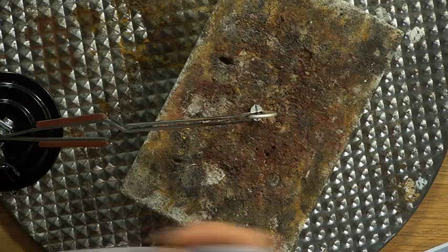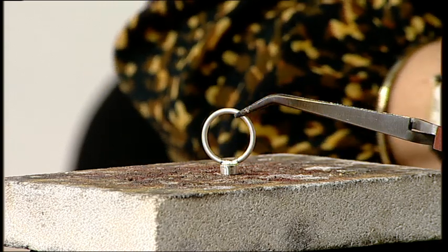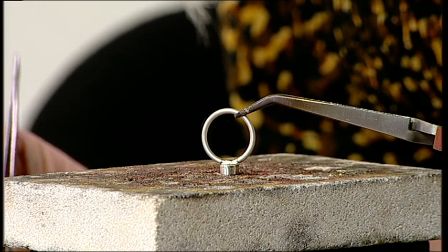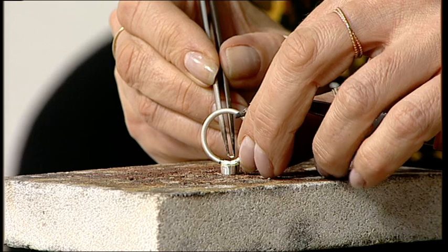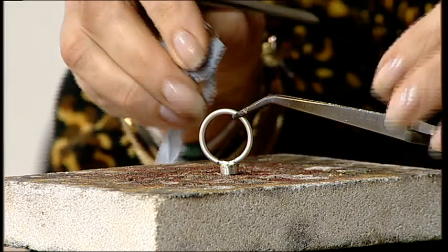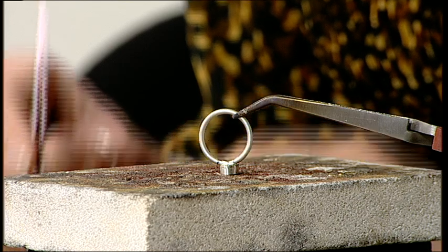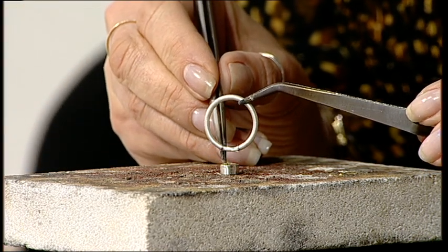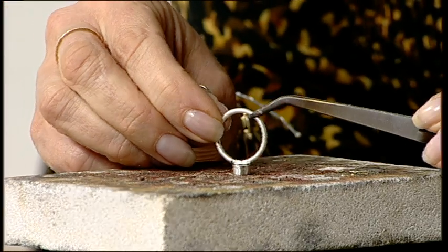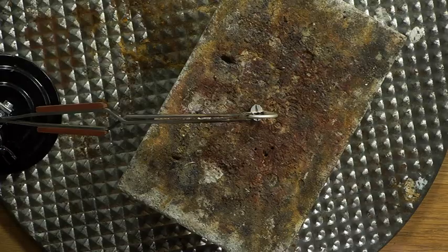Although you're at the final bits now, it's best not to rush this stage so you get it nice and neat. If it ends up a little skew, you can heat it up, take it off, and pop it in the pickle. In between each soldering stage you would pickle everything to take off the oxide. Troubleshooting tip: if you're having problems with soldering, make sure you've got solder on there, everything's touching, you've used flux, and you've pickled in between - almost like having a checklist.